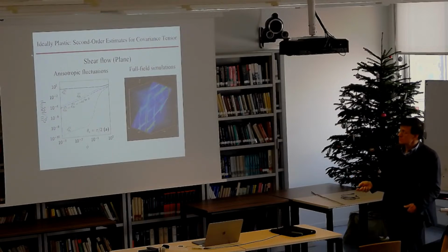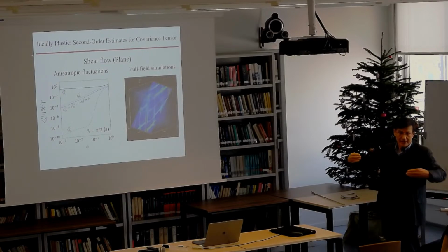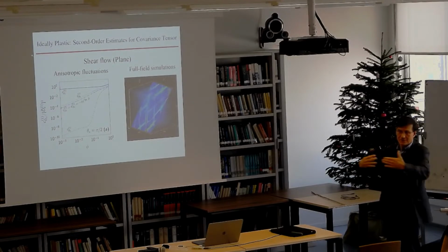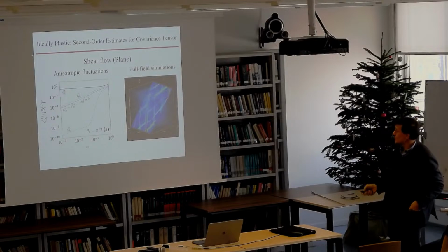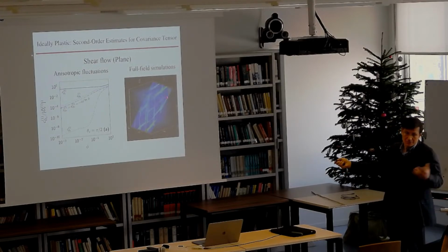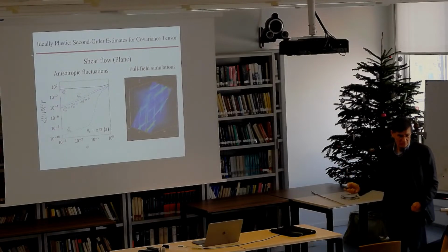But in the other modes, the fluctuations decay very quickly, because if the bands are straight, the rest of the material is flowing like a rigid block, so there's no deformation. The method cannot tell you where these shear bands are relative to the particles, because we don't know where the particles are, but it can give you information on the distribution of these shear bands.